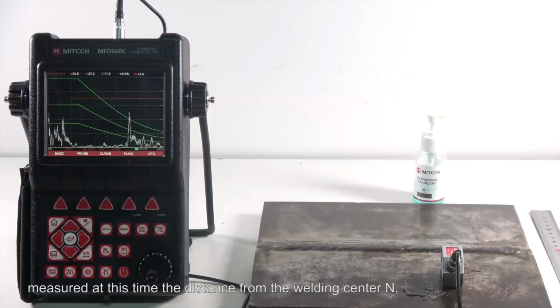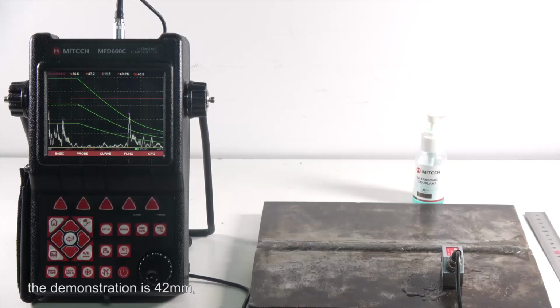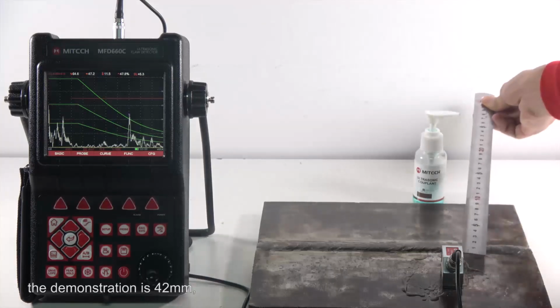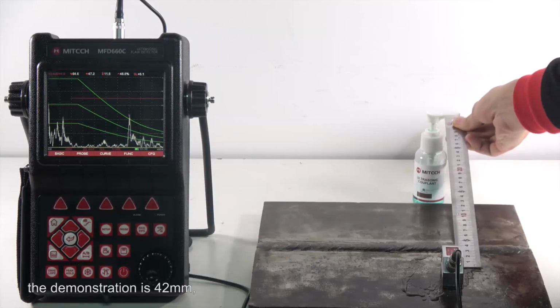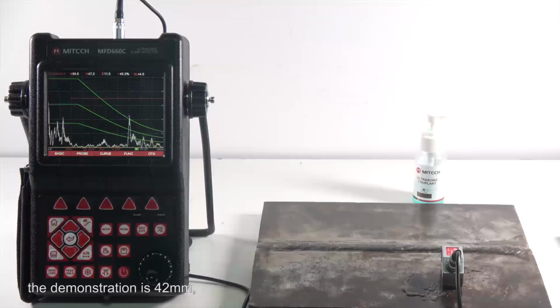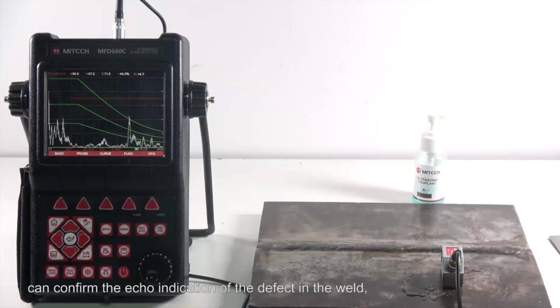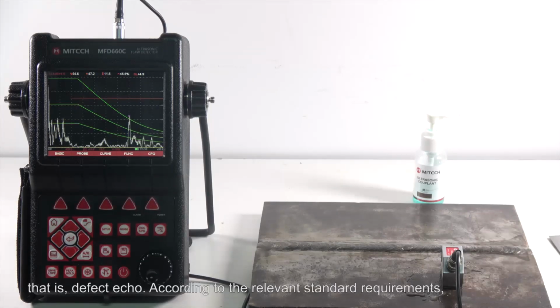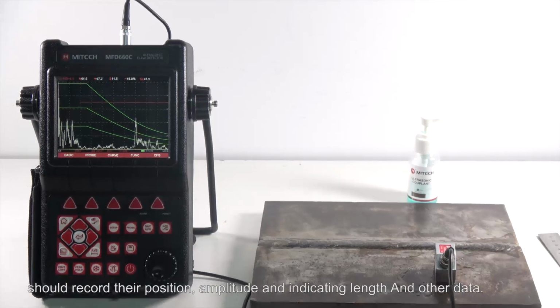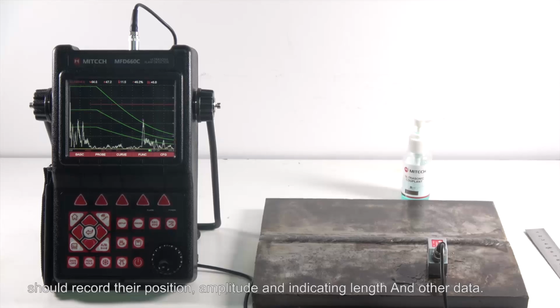Measure the distance from the weld center at this time. The demonstration is 42 mm. This confirms the echo indicates a defect in the weld. That is a defect echo. According to the relevant standard requirements, for defects whose amplitude reaches or exceeds the assessment line, record their position, amplitude, indicating length and other data.